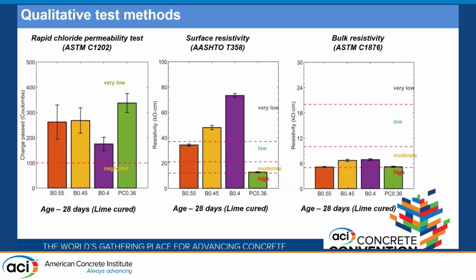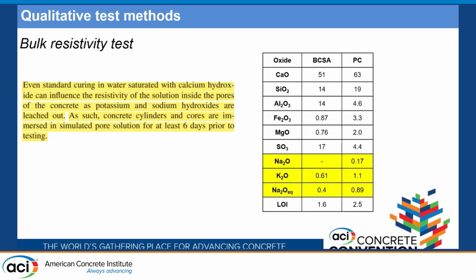What could be the reason for this change in BCSA specifically? One possibility could be the specimen conditioning. Because if we go with the standards, it suggests that we need to immerse the specimens in a simulated pore solution, which contains calcium hydroxide, sodium and potassium hydroxide. And I've taken a statement from the code that this is done specifically to account for the alkalis that were lost in the curing process, even if you use lime saturated curing.